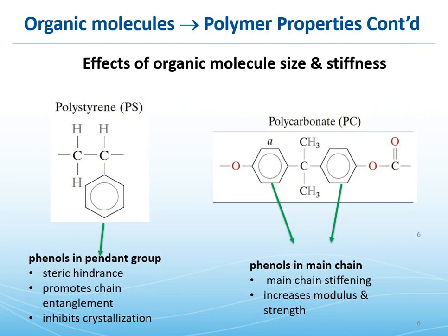It'll prevent it from crystallizing completely unless those phenyl groups are present in a very regular pattern. So this is why polystyrene is amorphous, again, unless those phenyl groups are arranged in an isotactic or syndiotactic arrangement, which is rather expensive from a synthesis standpoint and costs extra.